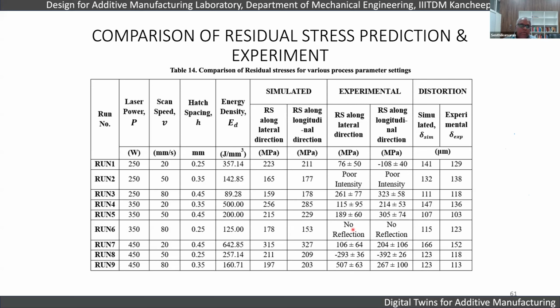For example, when we use XRD, which is only a surface measurement, we have done measurements before cutting, after cutting, and also after stress relieving. But we have only compared the residual stresses that we measured before cutting, because otherwise the stresses would have been relieved. We have seen that even the simulations before cutting could not yield comparable results in some places. So we have found that there's a drawback in using stress values from the commercial tools.